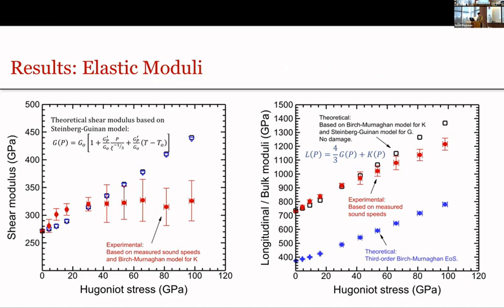So if we look at the shear moduli obtained from the experiment, the evolution of shear modulus as a function of Hugoniot stress is shown in the figure on the left. The blue symbols represent the theoretical shear modulus value as a function of pressure given by the Steinberg-Guinan model. This model assumes that there's no damage accumulated in the material. However, if we look at the experimentally measured shear moduli using the sound speed, which is represented by the red symbol, there is a large discrepancy.